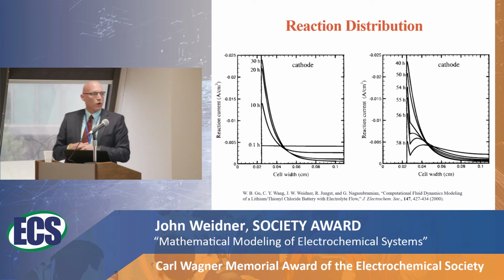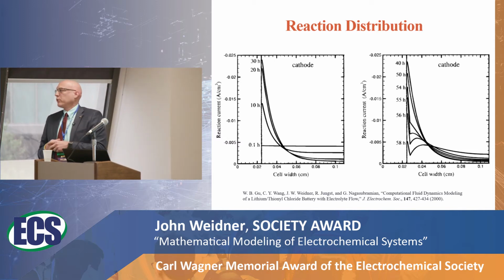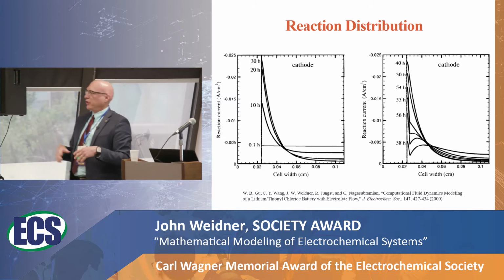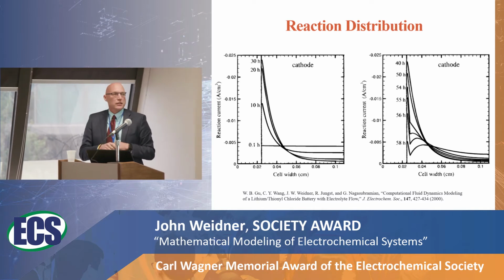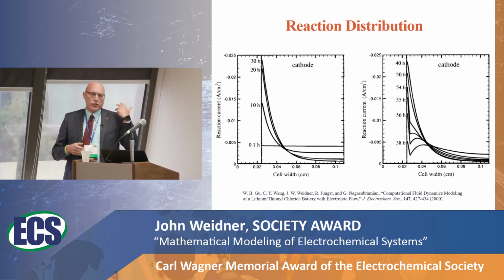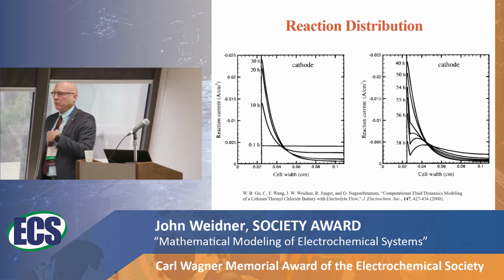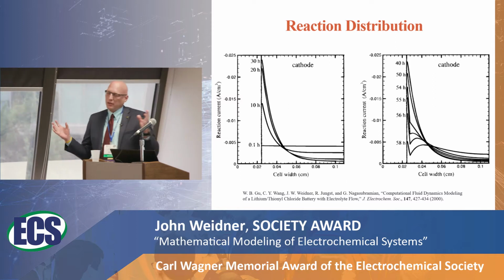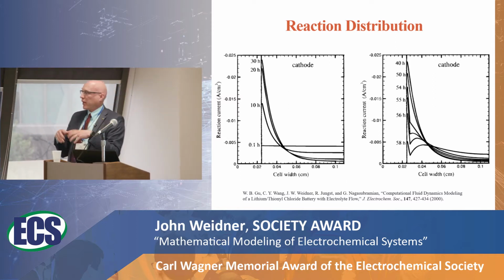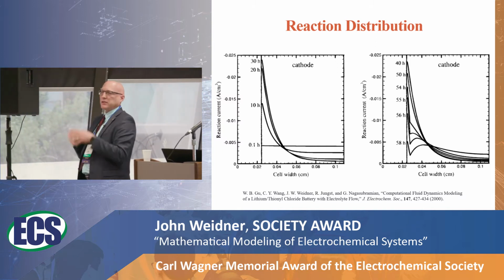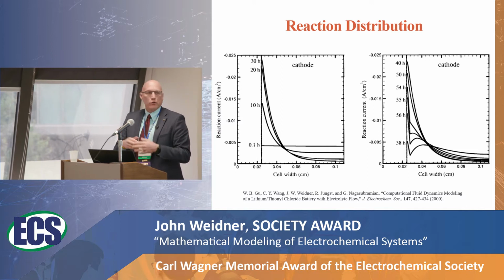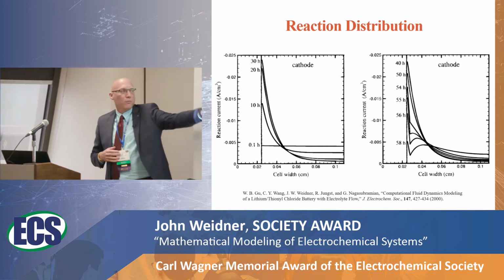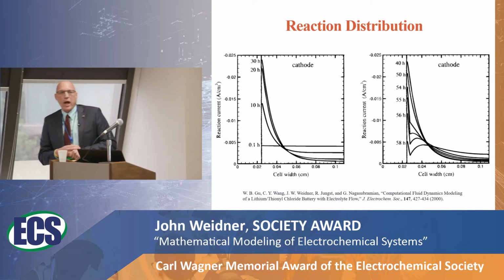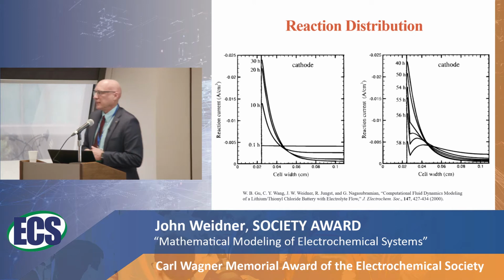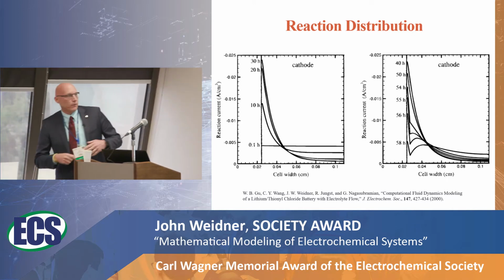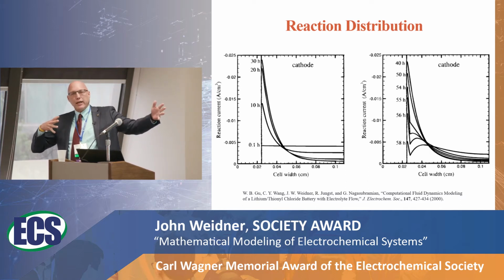But the main thing is we have this non-uniform distribution in reaction rate, and the reason, as we're familiar with porous electrode theories, is you get reactions occurring at the front face because it's ohmically limited in the electrolyte phase, so you get a lot of reaction at the front. Now remember, wherever the reaction is occurring, you're depositing a solid material. So all of a sudden, at the front of the electrode, not only did you have a lot of reaction there, but that's where the porosity starts to drop, accentuating the non-uniformity. So early on, you may have something fairly uniform, but it becomes very non-uniform over time because you're closing the pores off inside the cell. And there's an interplay between the experimental data that you're collecting and the models.